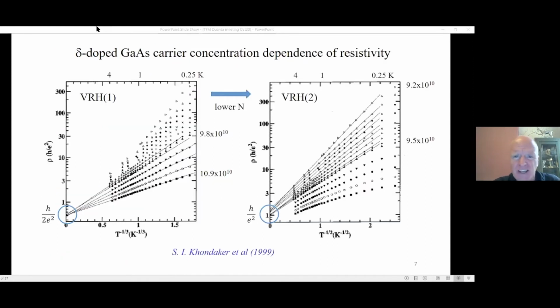Looking at some of the early experimental data on this, this is a delta-doped 2D gallium arsenide system. The delta-doping adds disorder, and it is very close to where the charge is confined in the 2D region. As the resistivity is measured as a function of temperature, this is 1 over T to the 1/3, so this is in the so-called Mott regime. At fairly higher carrier densities, it behaves as if it's variable range hopping through the Mott mechanism, so non-interacting charges.